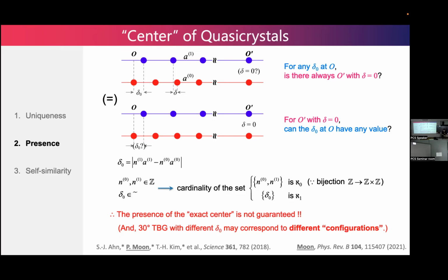Of course, in addition to this mathematical discussion, in a real material we probably also need to consider lattice relaxation. Yes, right. Like yesterday, Professor Koshino already mentioned, if delta equals 0, that corresponds to AA stacking, right? So that energy cost will be the highest. Is it possible that for 30-degree stacking, the system will try to avoid generating a delta equals 0 point? But then I guess there would be some domains. If you have a delta equals 0 center, the entire sample will be a single domain, in whatever sense of the domain.